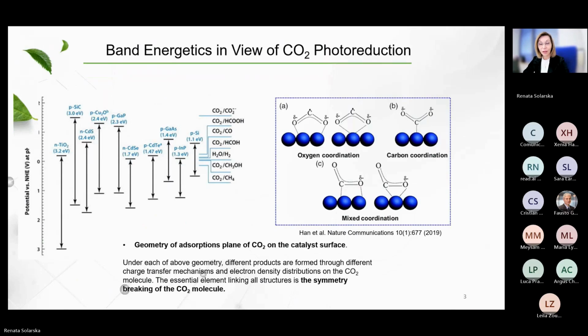But it's not a simple story to break the symmetry of the CO2 molecule, and this is the condition for the transformation of CO2 towards valuable products, and especially a precondition to get the C2+ products. Breaking the linear condition is determined by the good adsorption and production of the CO radicals. And from a theoretical and experimental point of view,